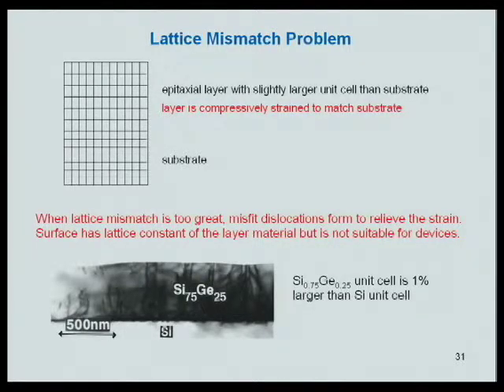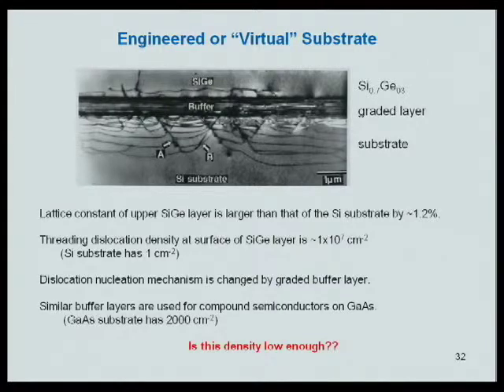So people all over the world working on lattice mismatch semiconductors have tried to come up with ways to avoid these defects. And one way is by grading the alloy composition so that we get a pretty good quality alloy layer on top of a substrate.